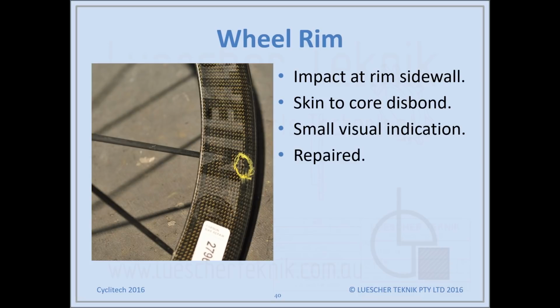Another rim, this is a lightweight rim. Now these are made with a very thin carbon skin over a foam core, and in this case there was some damage to the skin to core bond. So the core crushed and debonded from the skin due to an impact. It was a very small depression on the surface, and then the area marked in yellow was debonded. In this case we could repair that, and the wheel could go back into service.